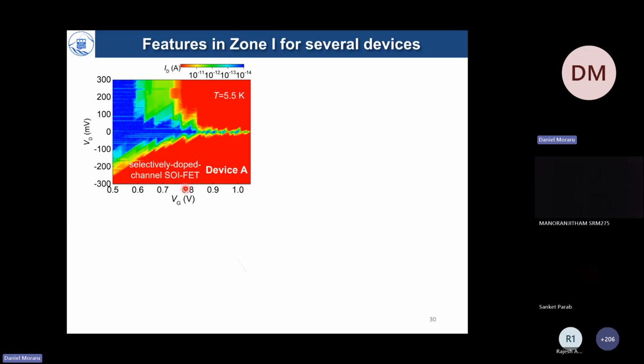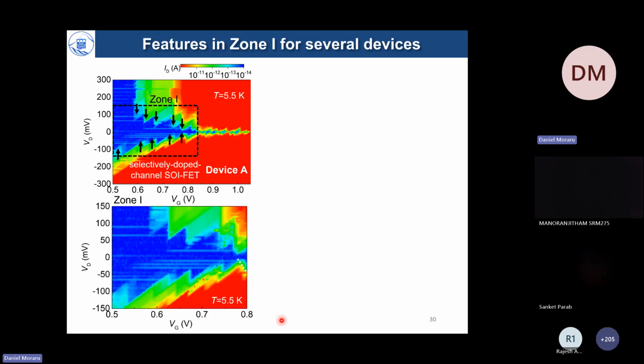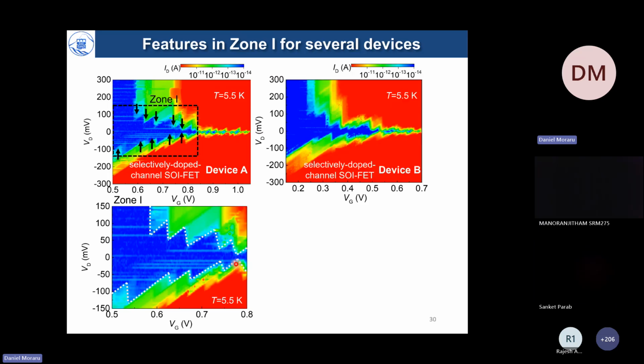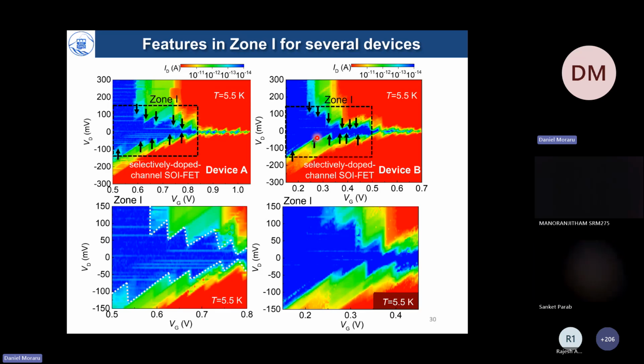So let me show you one device. For instance, this is a selectively doped SOI-FET device A. We observe this pattern, the same device that we explained earlier. And this is a zoom in on this zone of interest, zone 1. What we observe here as dashed lines are these open diamonds that I will explain a bit later. Another device exhibits similar but different behavior in terms of voltages and pattern. But nevertheless, we have two zones, zone 1, which contains these broad open Coulomb diamonds.